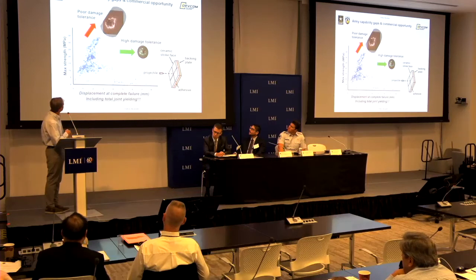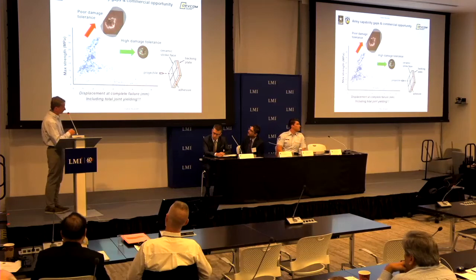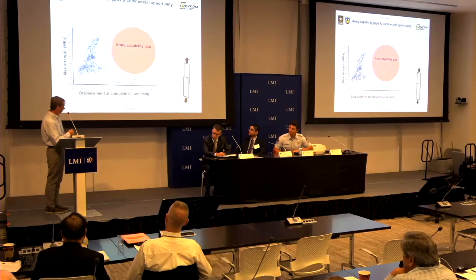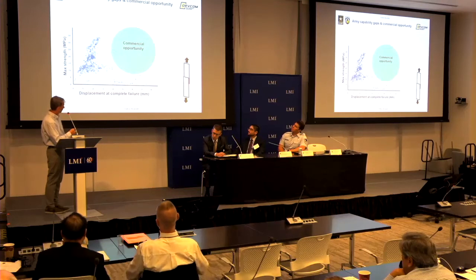So again, aerospace is going to trend this way, but this is just a flash X-ray of one of our ballistic targets. There's a lot of delamination around the neighbor. But when we were out in this region, the damage tolerance was very, very high. All right, so that's an Army capability gap. An Army capability gap is a commercial opportunity because these are all commercial adhesives, and we didn't see any adhesives in the commercial space that were fitting our needs.